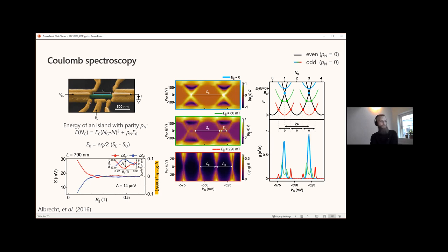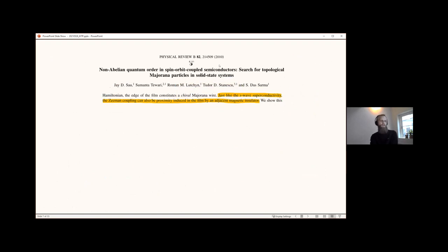in these hybrid nanowires. In parallel, or actually slightly before, the two popular proposals that I introduced before, another proposal was put forward that argued that just like the proximity-induced superconductivity, the Zeeman coupling can also be proximity induced in the film, and they mean the semiconducting film, by an adjacent magnetic insulator. So this is the idea. You have a semiconductor proximitized by the superconductor and magnetic insulator on either side, and effectively we recover this helical gap that can also be used for inducing topological superconductivity in these systems.